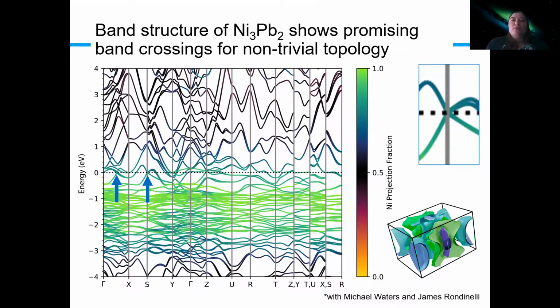One of the first things we did was look at the band structure, and we noticed that there are some pretty interesting band crossings for non-trivial topology. Although this is not a clean Fermi surface, in the sense that there are many, many bands crossing the Fermi energy in addition to our non-trivial crossings, we think that continuing to investigate phases in this family could help reveal strategies for cleaning up the Fermi surface for non-trivial topology. And in fact, some of the other B8 type compounds do indeed have slightly cleaner Fermi surfaces. So that's an area that I'm hoping that our group will explore at some point in the future.